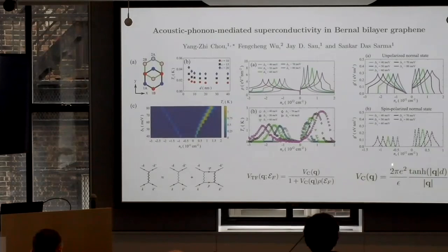All our calculations in bilayer graphene and in TMDs include this Coulomb interaction, because there are always gates, okay? But this gives rise to very small mu star. So this doesn't explain experiment. Look at the Tc we are getting here. Tc we are getting is of the order of 1 Kelvin. And look at the experiment. Tc is 40 millikelvin, right? So this is a huge difference.